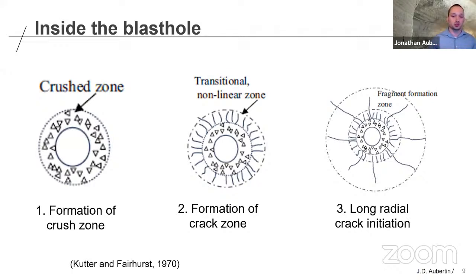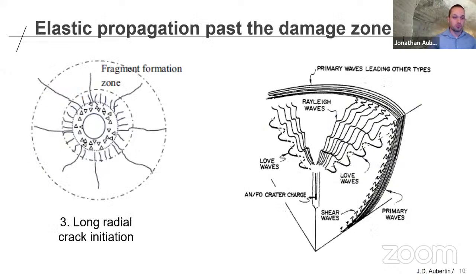Then further along, you have this transitional zone that is not quite pulverized, which has a bunch of radial fractures, but is still highly damaged. Then you have a zone that is more important for all the practical application of blasting, which is the fractured zone where you have a series of radial fractures emanating from the blast hole section. This fragmentation zone, these radial fractures, is not particularly large. You're not destroying the rock mass, and it's not the primary means of fracturing for extraction, but it's very important from what takes place downstream.